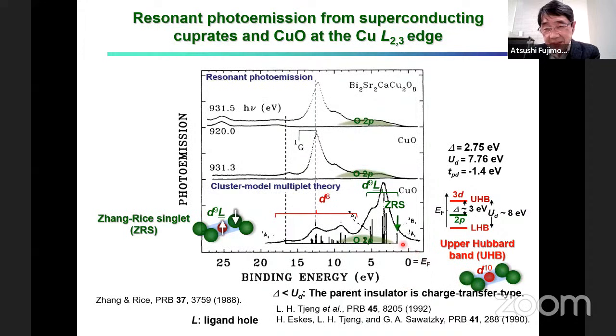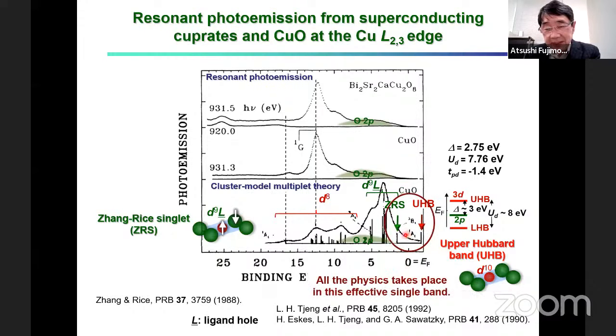And the empty state, which cannot be seen by photoemission, is supposed to be a few eV above the Fermi level, the so-called upper Hubbard band, with D10 configuration. So all the low-energy transport properties are determined by these two states. The degeneracy is one for the Zhang-Rice singlet, and because this is a singlet, there is no spin or orbital degeneracy, and the upper Hubbard band is filled D10, so its degeneracy is also one.